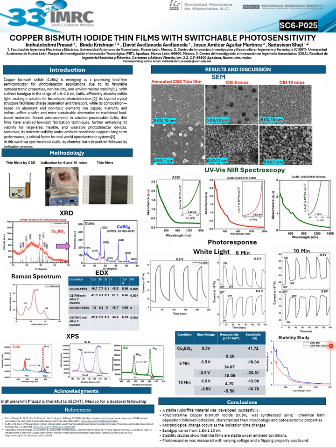This material is stable for more than 20 days. There is only a slight difference in the intensity of the UV visible, and from the EDAX we also observe only a slight change. This implies that this material is a stable material, and it is a promising candidate for photodetector application.